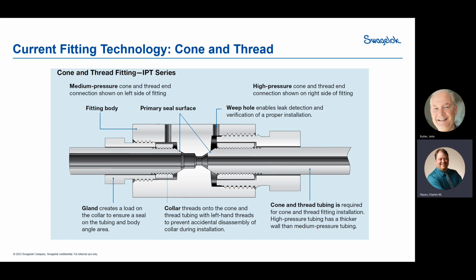How does this thing work? Here's how it works. Take a piece of tubing, you put a cone on the end of it, you put a left-handed thread behind it, and you put this little collar onto that left-handed thread. Then you use the gland or nut to push the collar, which pushes the tubing into the cone surface, into the chamfer that's inside the body of the part. And the thought there is those two are going to slide together and create a long seal. The reality is that's not what happens.